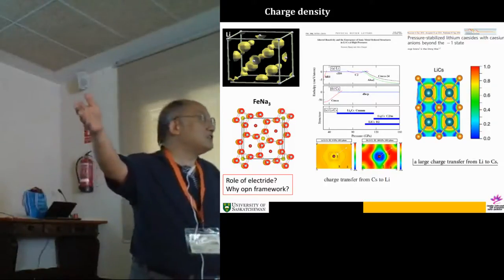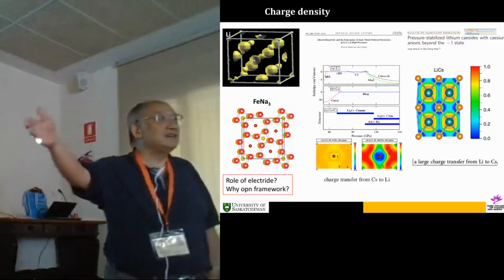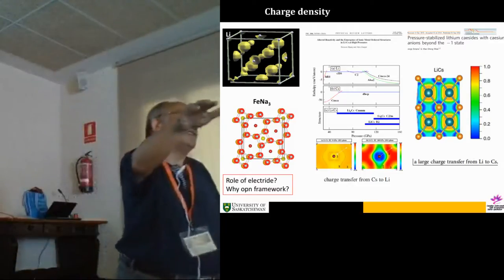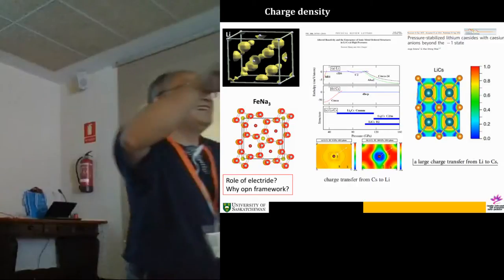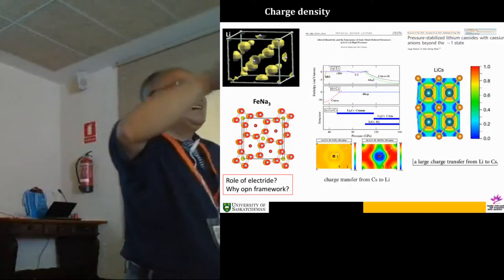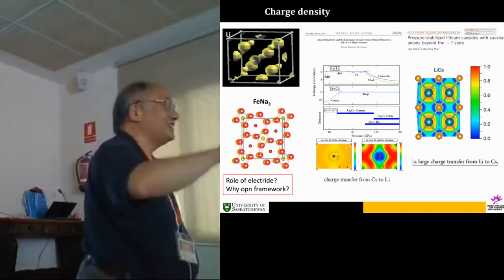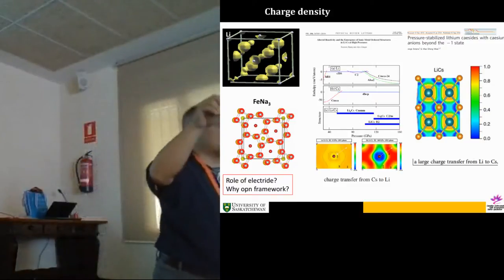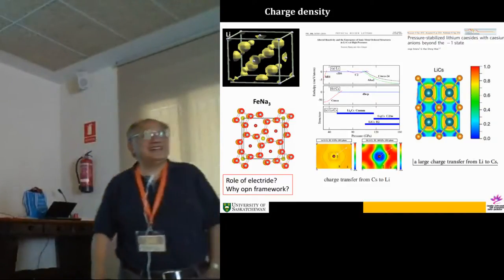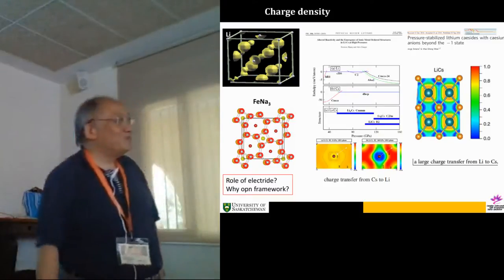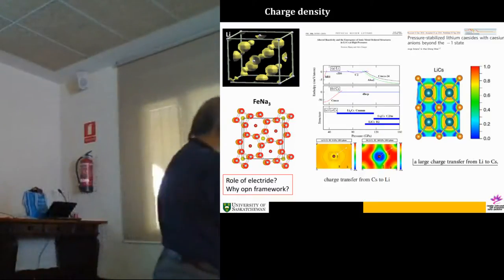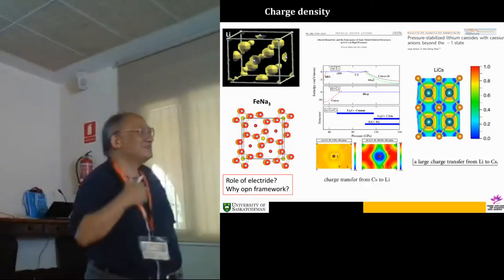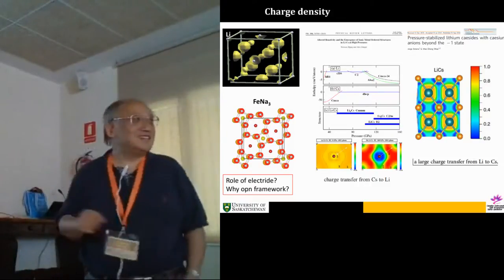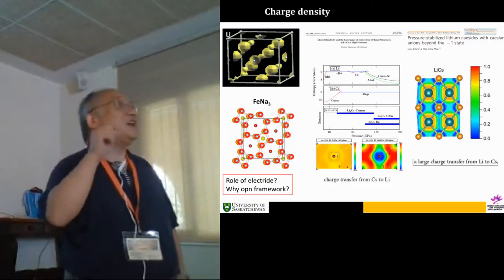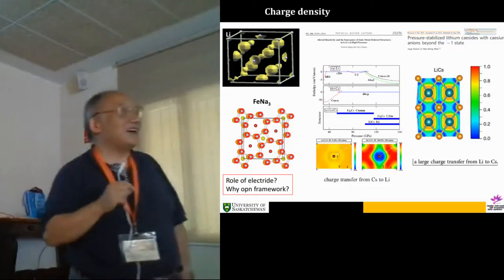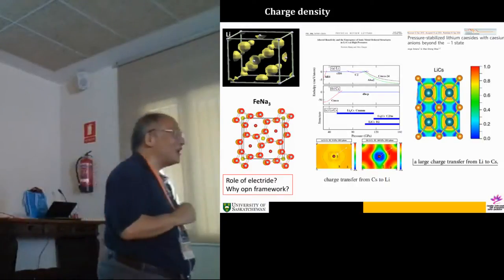Has anybody looked at the International Tables Volume 2, the red book? Well, right now the blue book. It's green now, I think. I'm third generation behind. Sorry. They're calculated with Hartree-Fock-Slater, not even density functional, all right? And they calculate as an atom. So one third of the scattering intensity has gone out into the interstitial, where there actually is no atom site. So you have to push through the atom. If I know the structure, of course I push through the atom and account for that scattering intensity. But you don't know how to do that.